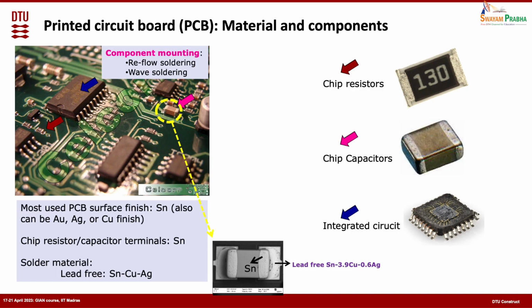It can be a surface finish with gold, or it can be silver or copper. Copper is very little used. The base layer on the PCB is always copper, but that copper is covered with something else on the top. Usually tin is the one mostly used, because when you put the component on top of this, soldering is done here like this. The soldering process also uses tin alloys, because tin is a low melting alloy.